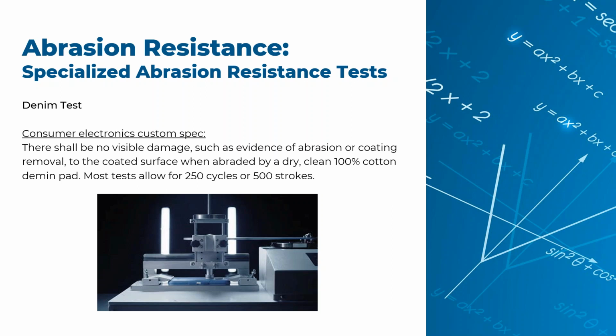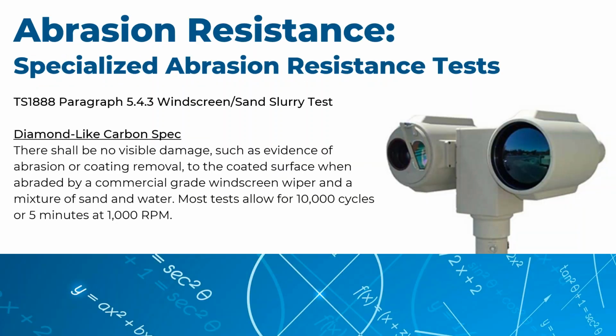Okay, I've swiped that 500 times. I'm going to take a look at this surface and see, did I alter the transmission? Is the coating cloudy? Am I creating stress in the coating? Do I lose adhesion? Different things of that nature. Are there clusters of scratches? Anything like that. So you're really looking for a weakness point in the coating.